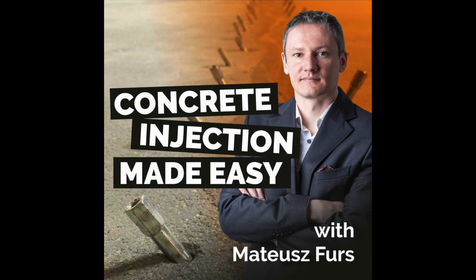When using surface packers, the crack should be sealed at its surface with an epoxy paste. It's another product. You use this paste also to attach the surface packer, remembering not to close the connection underneath the packer so that the resin may penetrate inside the crack while injecting. You can place a nail inside the packer and inside the crack to make sure there will be a connection after gluing. Remember to remove this nail before the resin cures.